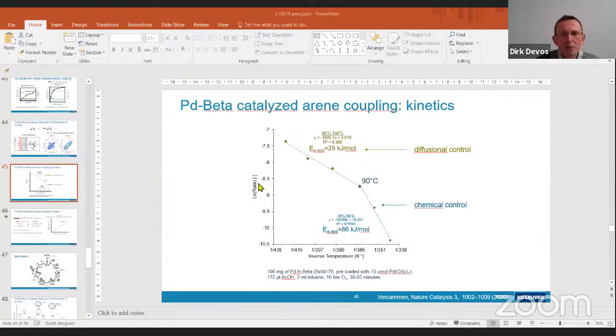Yes. Well, this is, of course, one of the classical tests that one could do. You vary the temperature, and of course you need to do this in the right conditions. But then you indeed see that we have a pretty high activation energy, 70, 80, 90 kJ/mol, pretty high. In catalysis with porous materials, this is considered too high for the process to be under diffusional control. If you read Mark Davis's textbook about this, at 80, 90 kilojoules per mole you are already pretty safely into chemical control, which means that all the palladiums that are active are not subject to diffusional resistance. If you go to higher temperature, we all know that a chemical reaction is more thermally stimulated than a diffusional phenomenon. And then we see this transition to a lower activation energy.